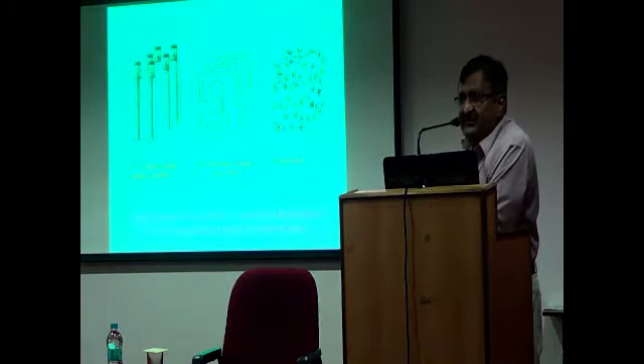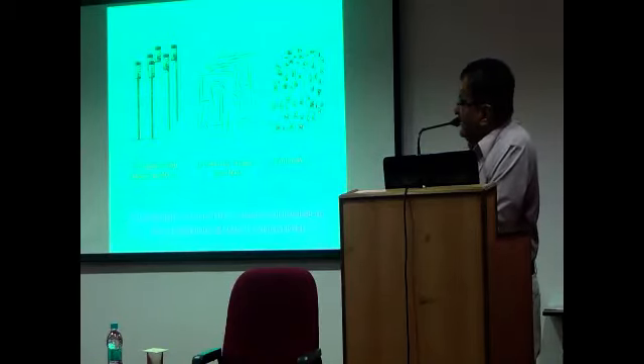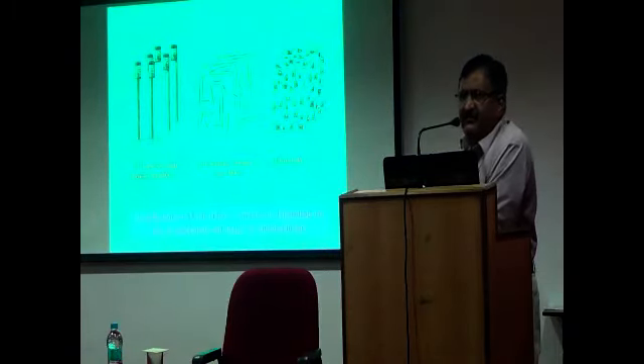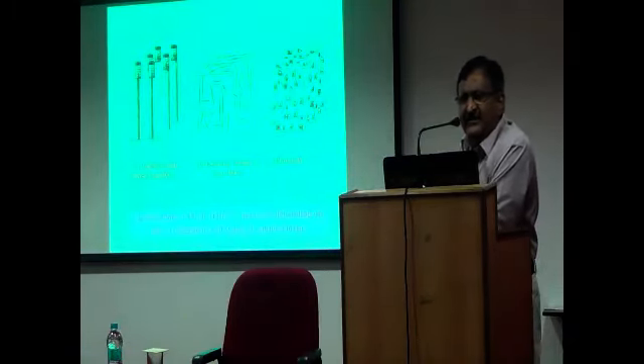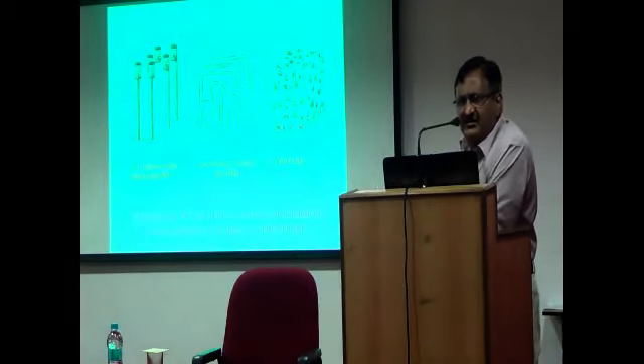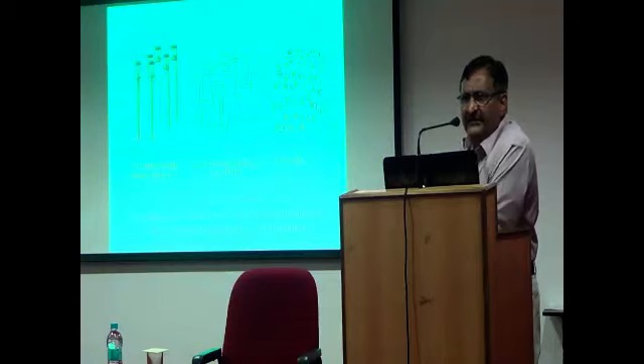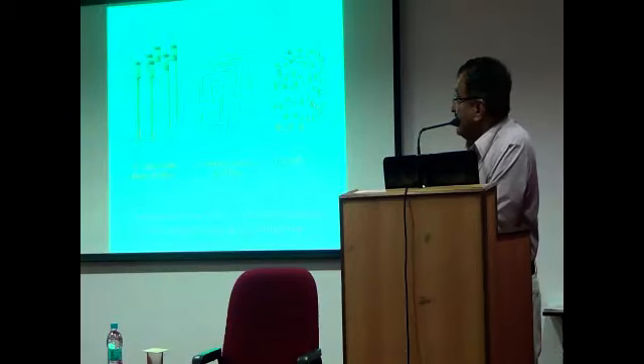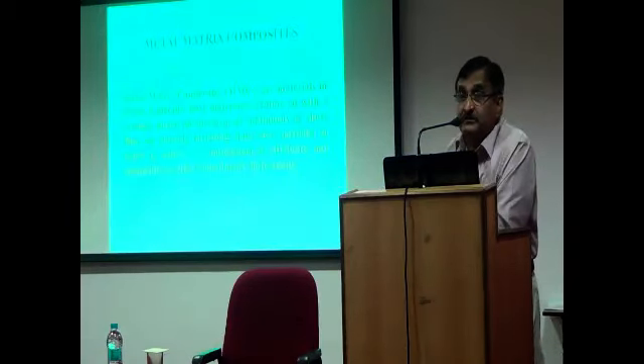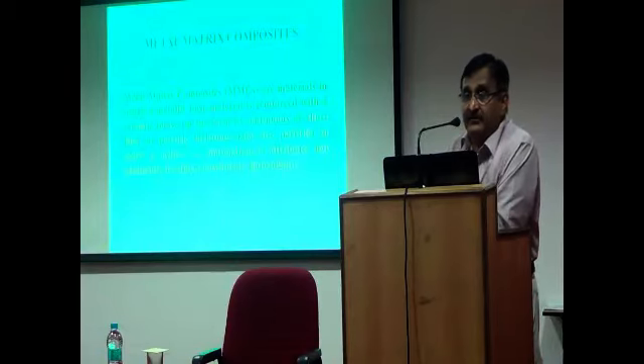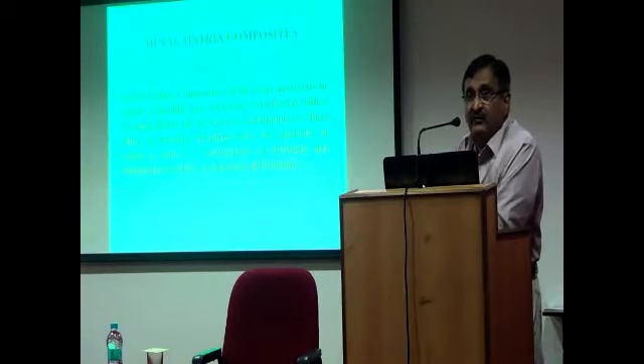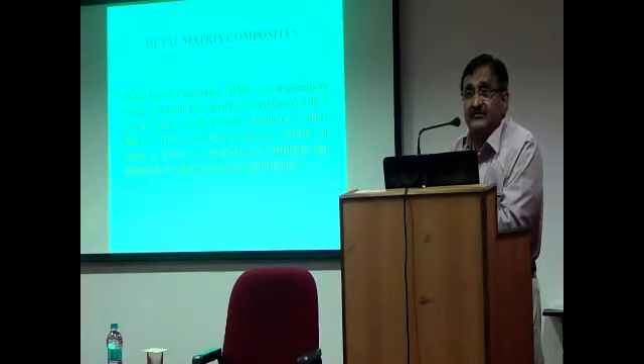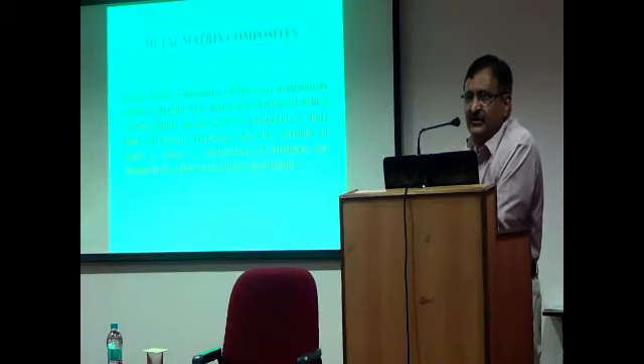The utility of these materials was explored for nearly 20-30 years, but somehow it did not really take off for several reasons. One is the fabrication difficulties, secondary forming difficulties, cost, and the problem of transverse toughness. All these things restricted the use of this kind of material. Moreover, fiber is very expensive to produce, and after producing the fiber, embedding it in the metallic system was much more difficult. Okay? And working this material into a desired shape is much more difficult. So it had very limited utility.